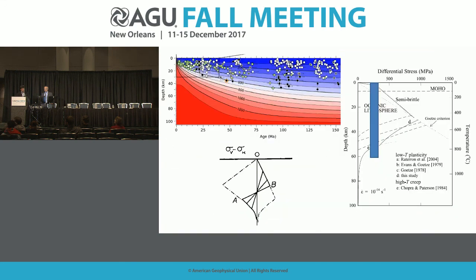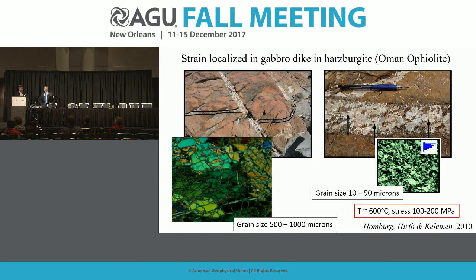So, since Peter asked that question, he's good at doing that kind of stuff. In that session yesterday, where a lot of amazing data were presented, it made me think of the outcrop we looked at here. Here we have a stress of 100 to 200 megapascals and a temperature around 600 degrees C, and yet we can't find any evidence of deformation in the peridotite here. So in one way, I'm more confident that while there's still a lot to be learned, and while we can get lower strength data with the type of modeling experiments from low temperature plasticity, they're not going to bring us all the way down to 100 or 200 MPa at geologic strain rates at 500 degrees C. That's the way I interpret that. But I could be wrong.